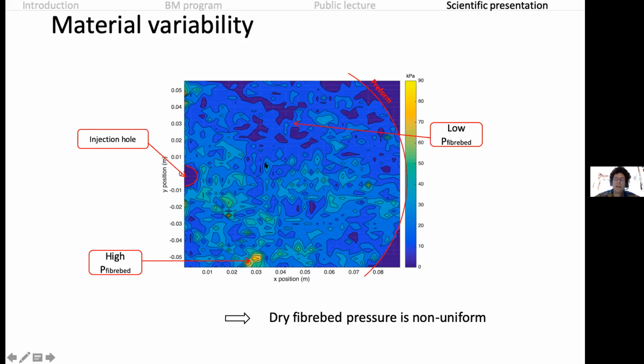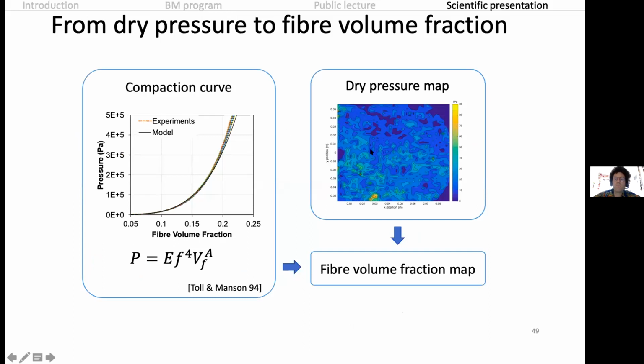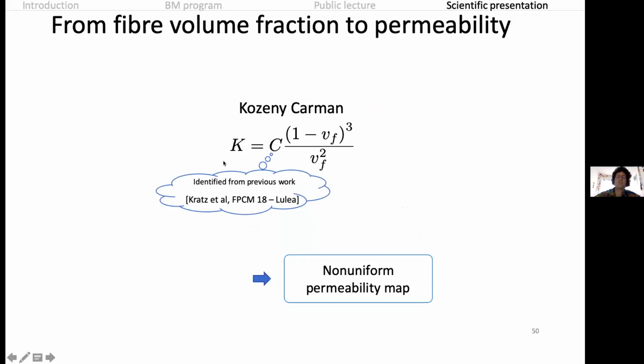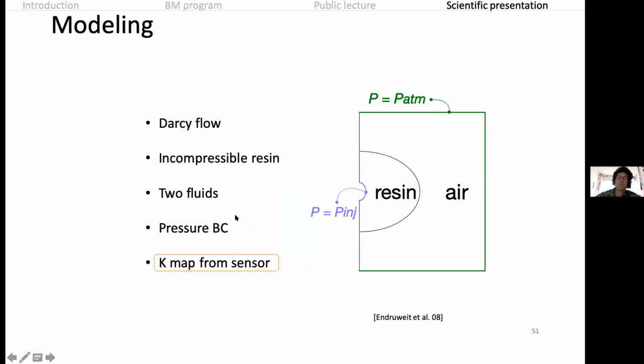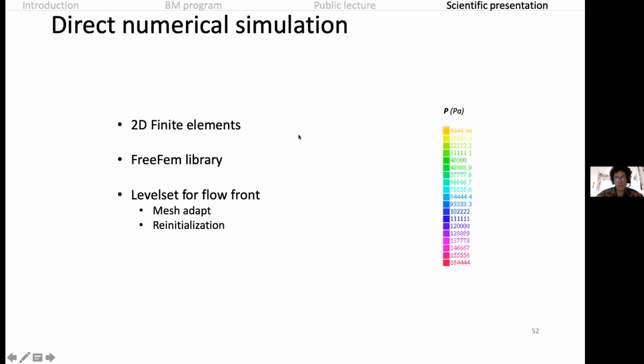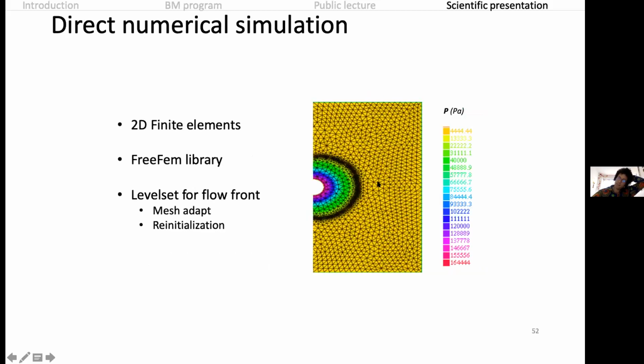We did that by solving the equations of flow. I'm going to skip the technical part, but if you want some details, this is all in the published paper. So we took into account the compaction curve and this dry pressure map that I just gave you. We can obtain the fiber volume fraction. The fiber volume fraction can give us the permeability map, and the permeability map can be used to solve for the flow. The equation of flow is called Darcy flow. This is the flow of a liquid inside a porous material. We solved that numerically inside a computer.